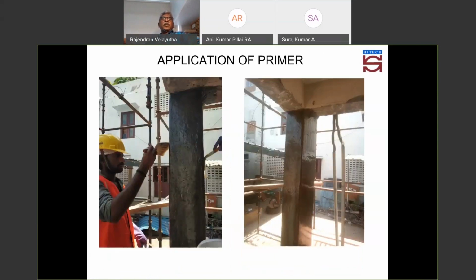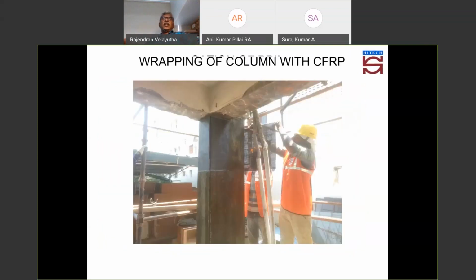And then you apply an epoxy primer. This primer is expected to penetrate into the concrete surface. As it penetrates, it acts as part and parcel of it. As this is an epoxy primer, I am going to use an epoxy glue for fixing my strip or wrapping. The primer is an epoxy, and my adhesive is also an epoxy, so it's like-to-like material, and the bonding is perfect. So you have to always choose a primer and adhesive of the same family, otherwise you will have a problem of debonding.